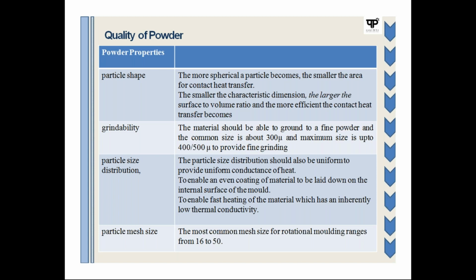Here, the smaller the characteristic dimension, the larger the surface to volume ratio, the more efficient the contact heat transfer becomes. So what I mean to say, depending on the size and shape of the product, slower or faster transfer of heat can be ascertained. Another part is grinding: the material should be able to be ground to a finer powder. Normally the common size you are using, in most cases from the data I have taken, is around 300 micron,